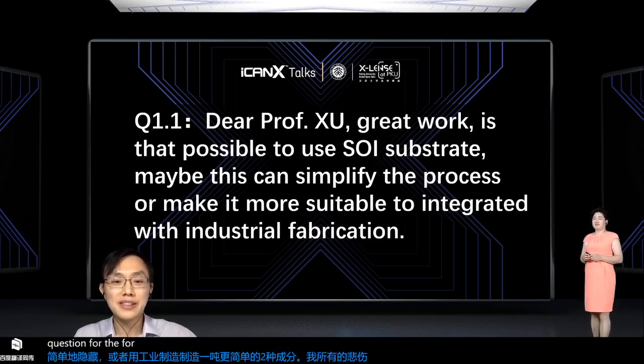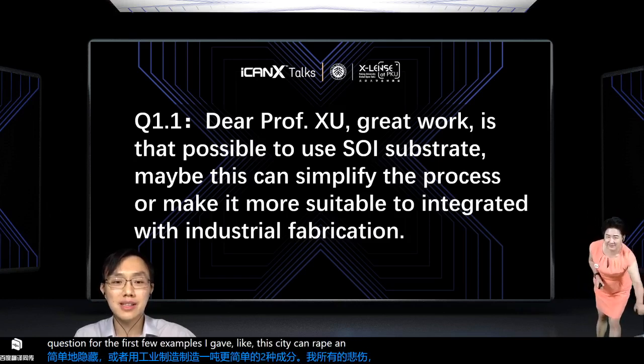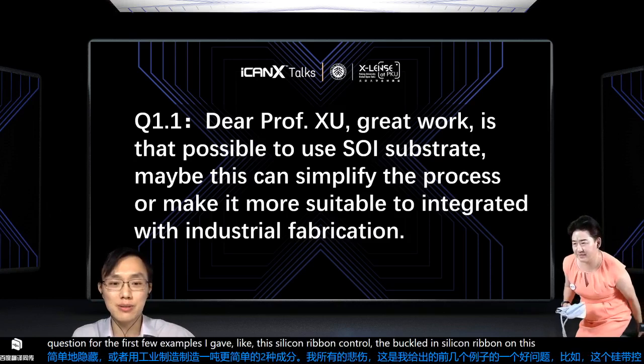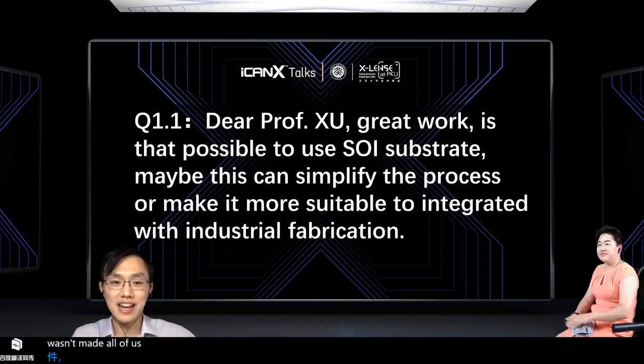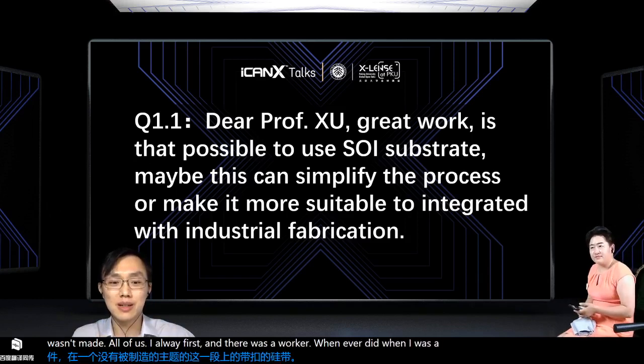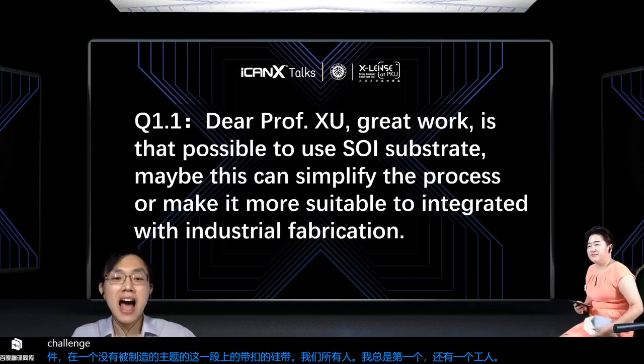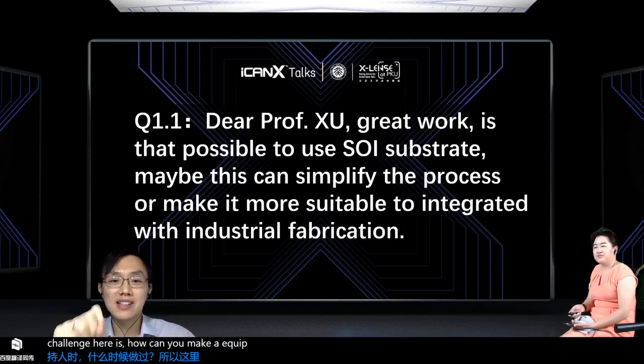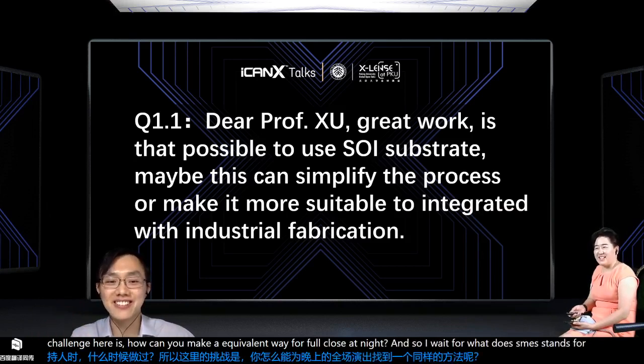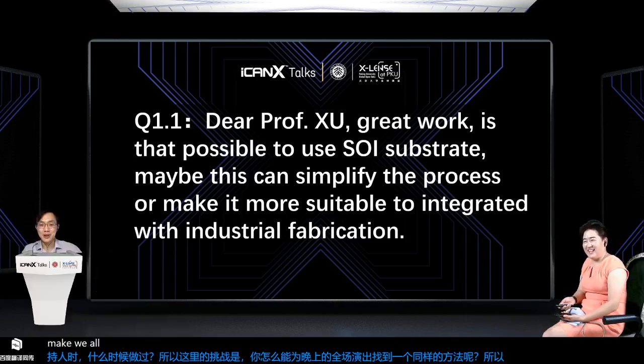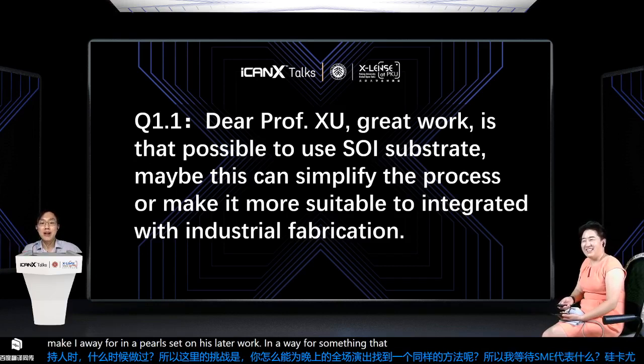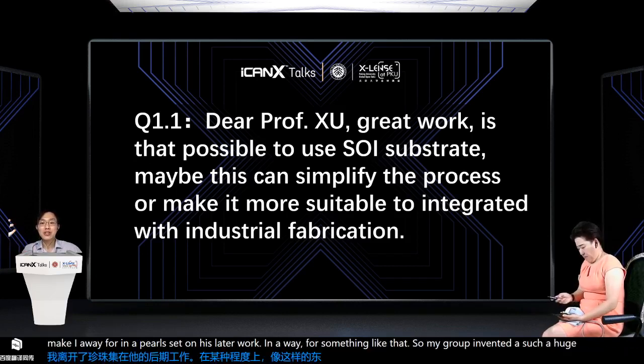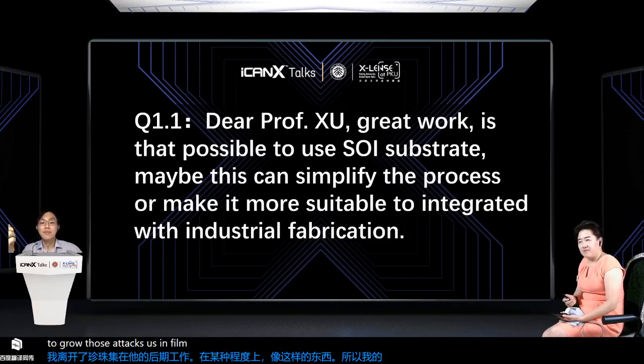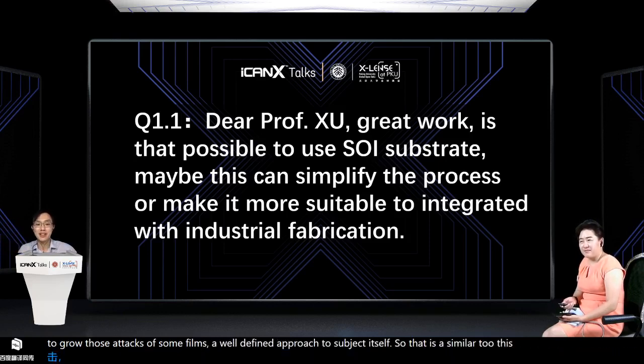For the first few examples I gave, like the buckled silicon ribbon on the stretchable substrate, that was made out of SOI wafers, and that was work when I was a postdoc in Professor John Rogers' group. So the challenge here is how can you make an equivalent SOI wafer for perovskite, right? S stands for silicon, right? Can you make a POI wafer, perovskite on insulator, something like that? So my group invented such an approach that allows you to grow those epitaxial thin films on a well-defined perovskite substrate itself. So that is similar to this SOI concept. So that's a good question.